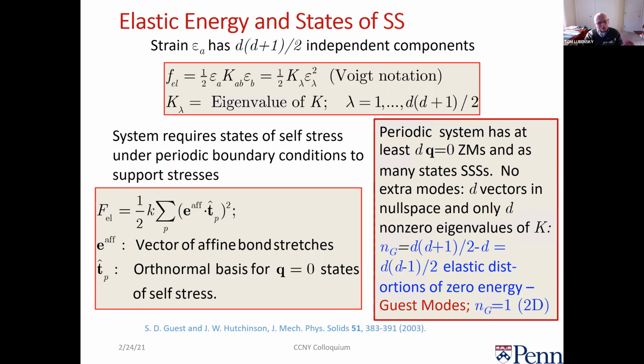a number that stays the same times, the easiest way to say it is, if I have a straight line of bonds like this, and I have an affine strain, they all move over like that, and I don't have any wiggles along there. That's not the zero energy state, but anyhow, you take the affine strain and dot it into the orthonormal basis for the states of self-stress. The calculation that comes out is that if, say, in two dimensions I just have two states of self-stress and not three, then I don't have enough states of self-stress to exhaust the total number of eigenvalues of the elastic matrix. And so in two dimensions you necessarily have one of these k lambdas which is zero, and that's the guest mode. And in three dimensions, there are three of those.